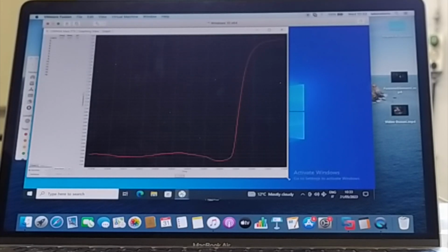After a certain time, we switch off the magnetic field. The temperature immediately decreases because the system dissipates heat with the surrounding environment. During a typical magnetic hyperthermia experiment, we collect the temperature of the water as a function of time for 1 hour during heating and for another hour during cooling.